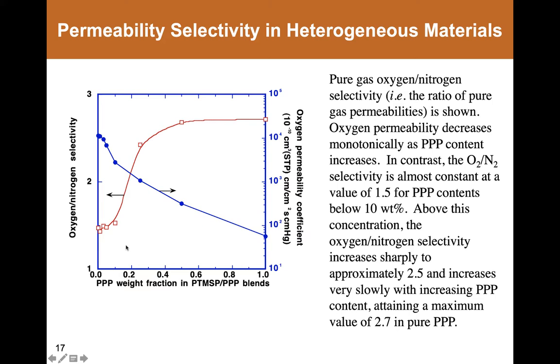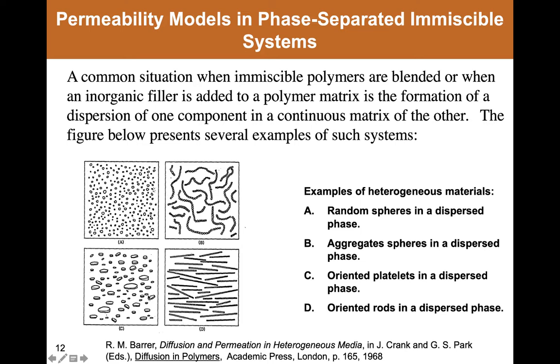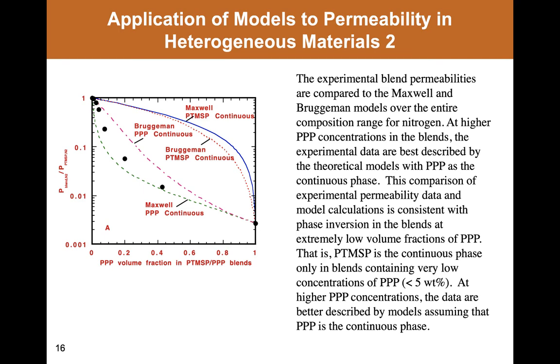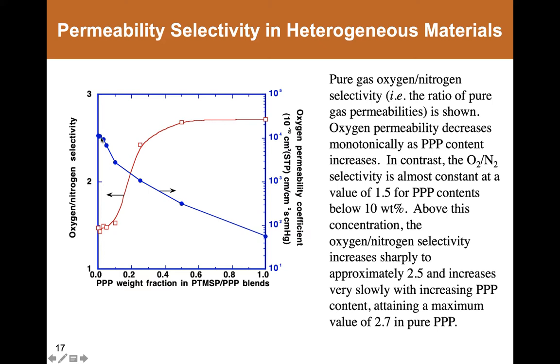At the very lowest concentration of polyphenylpropyne in PTMSP, this blend is phase separated, and the polyphenylpropyne is present as a discontinuous phase in the PTMSP. You might envision it a bit like, turns out it's a bit like there are polyphenylpropyne platelets dispersed in a background matrix of PTMSP. And as a result of this, the gas permeation properties are dictated basically by the permeation properties of PTMSP. At about 20 weight percent, you see a large increase in selectivity. And this is the point where this blend phase inverts. And at compositions at least from 50 weight percent on to 100 weight percent, there's almost no change in selectivity.